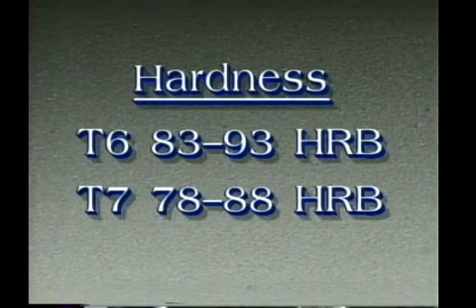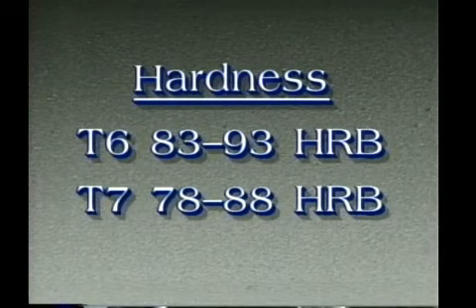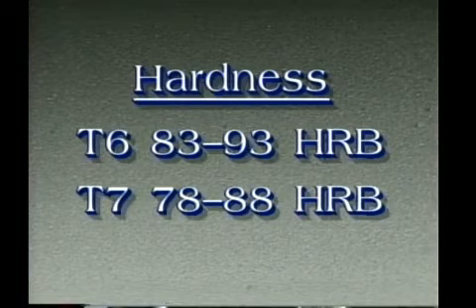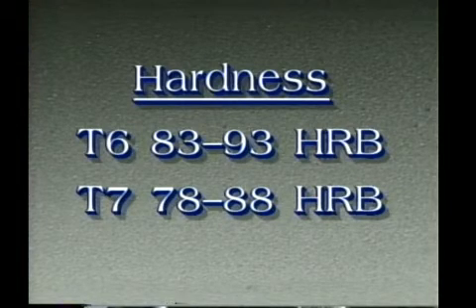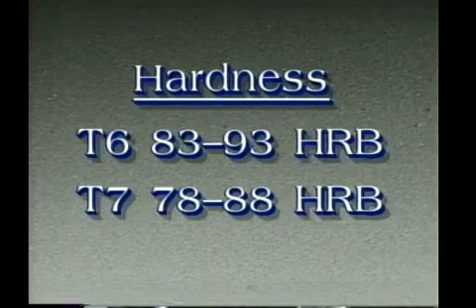Thus, an overlap occurred in the range of Rockwell B 83 to 88, so that materials heat-treated to a T6 or T7 temper could both show hardness readings in that range. So, if a heat-treated part would have a Rockwell reading of 85, the aerospace inspector would have no way of telling from the hardness reading alone if the material were T6 or T73. The hardness test was therefore not sensitive enough to positively discriminate and verify that the part had been overaged to a T7 temper and would be resistant to stress corrosion cracking problems.